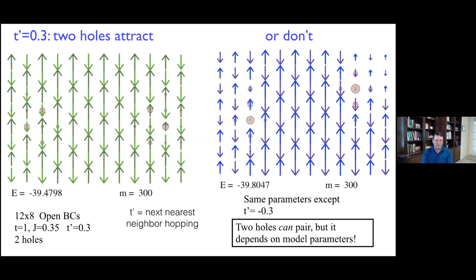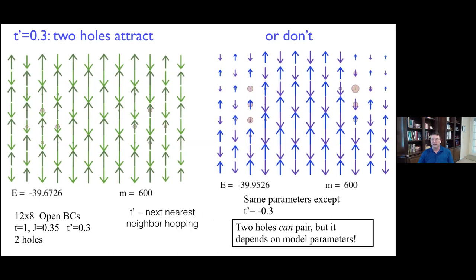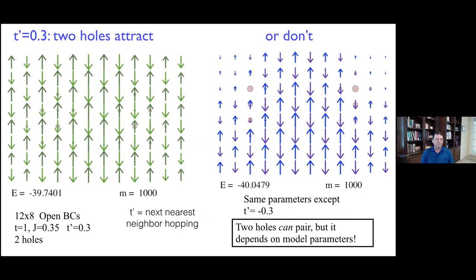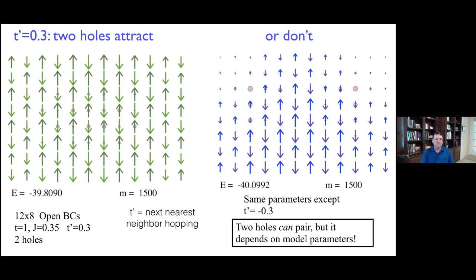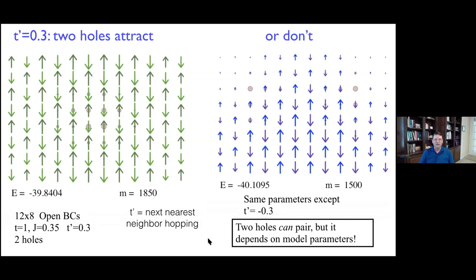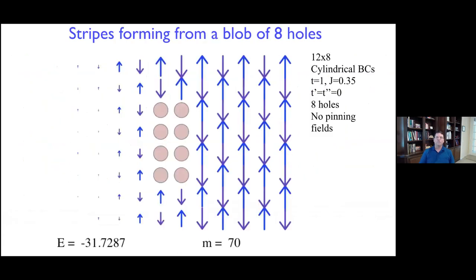And you see this pair of holes just forming one packet in the center. But with T prime negative, the two holes simply stay far apart. So this is a very clear-cut way to see that there's certainly a tendency in this case for these holes to bind into these pairs. Okay, now let's look at the case where we put in more holes.